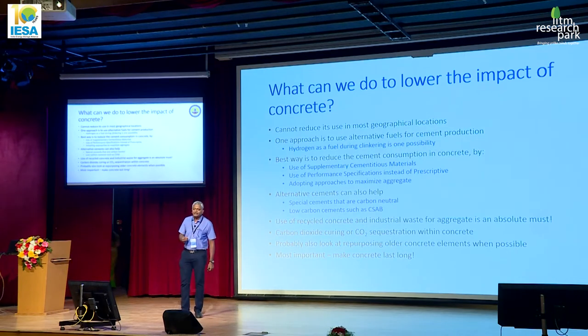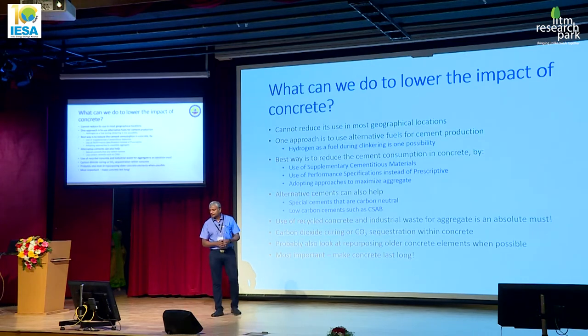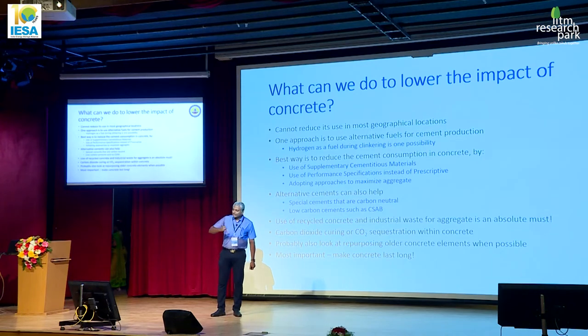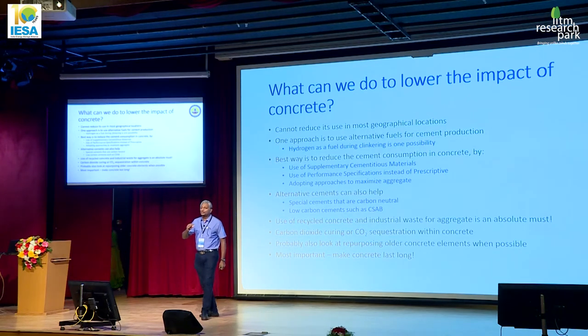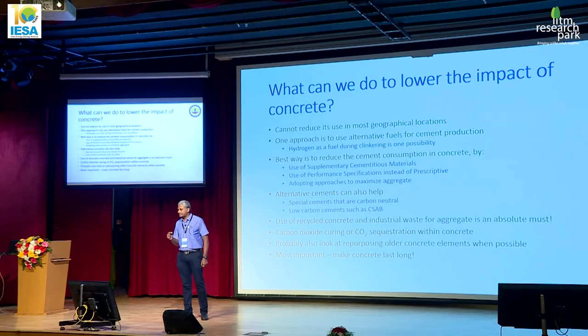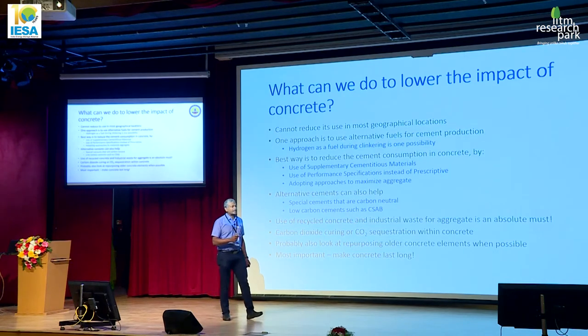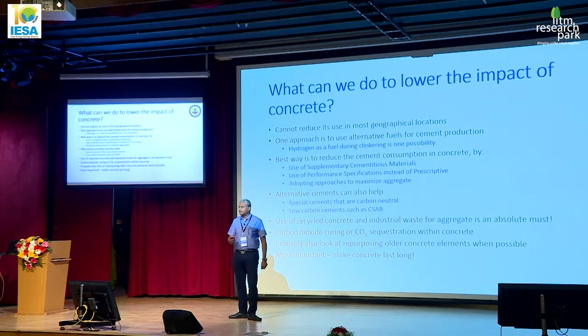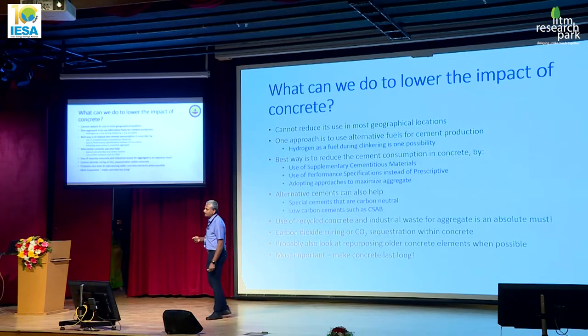So one possibility here, as we are going more and more towards hydrogen-based fuels, is the use of hydrogen as a fuel during clinkering. The part on the clinkering itself, you really can't do too much about, because the chemistry of cement is such that you need a majority of the raw material to be limestone. You need mostly calcium oxide to make your cement, and we can't really do without the limestone.